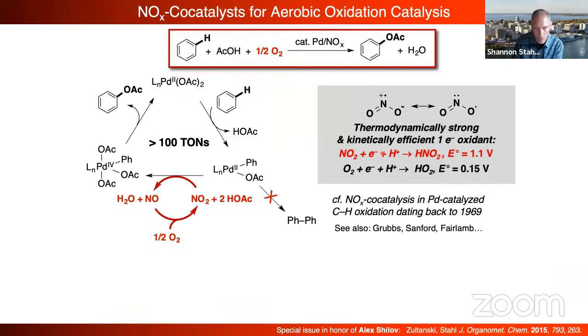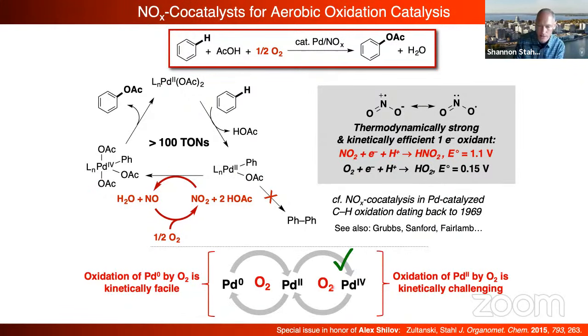And keep in mind what's basically happening. I mentioned O2 to superoxide, 0.15 volts. So if you try to dock O2 onto a palladium-2 center, there's just not the driving force that's going to get you anywhere close to palladium-3 up to palladium-4. Whereas nitrogen dioxide, 1.1 volts. You've got almost a volt extra driving force to kick this up into high gear, get it into palladium-4 so you can now make a C-O bond. And so that basically says that by using this type of NOx redox couple, you can now access this palladium-2,4.